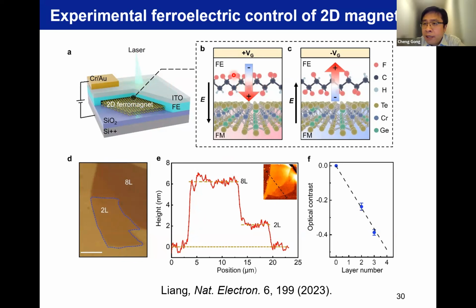When you flip the ferroelectric polarization of, for example, this PVDF-TrFE, you actually have a different interfacial configuration. Here, you have hydrogen and fluorine in direct contact with the 2D magnet, but in the other polarization, you only have fluorine. So the ions are moved, and the interfacial bonding and the crystal field are totally changed. We know magnetocrystalline anisotropy arises from spin-orbit coupling and the crystal symmetry. Once you change the crystal field, you are changing the contributions of different orbital moments, and when they couple with spin, that will change the magnetic anisotropy.